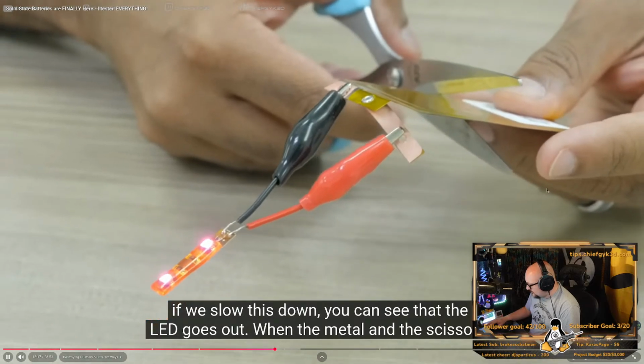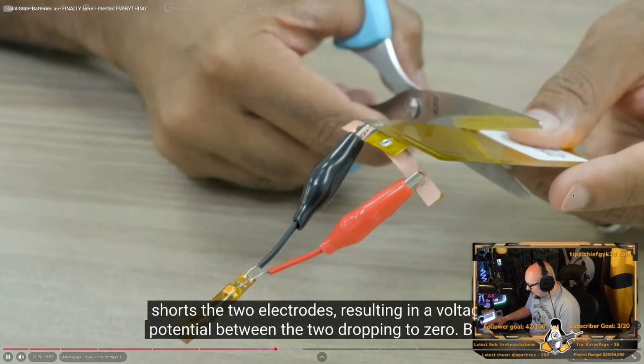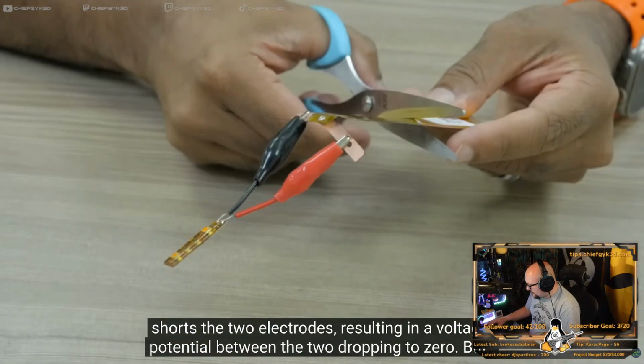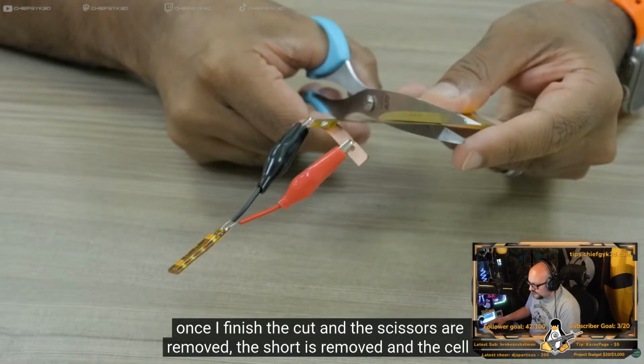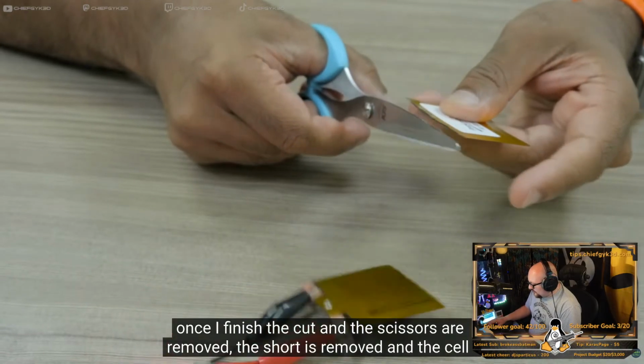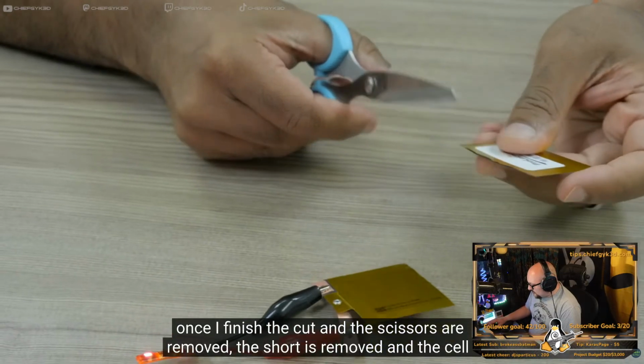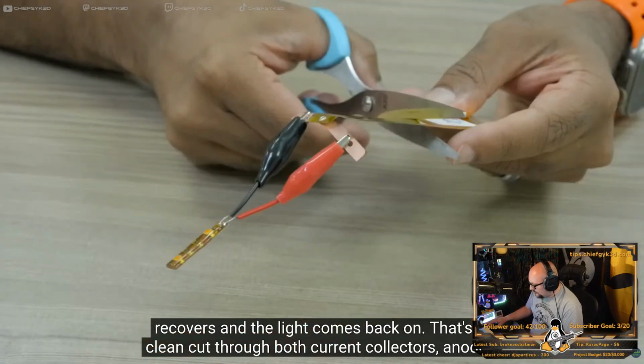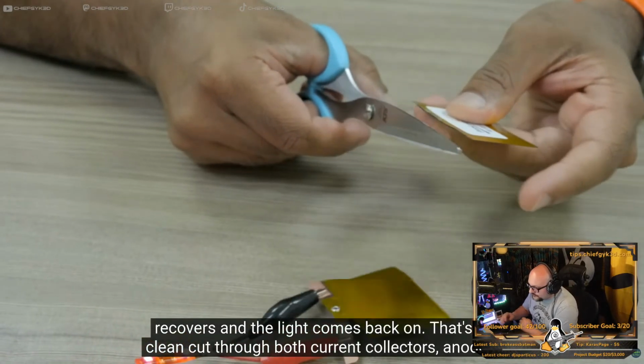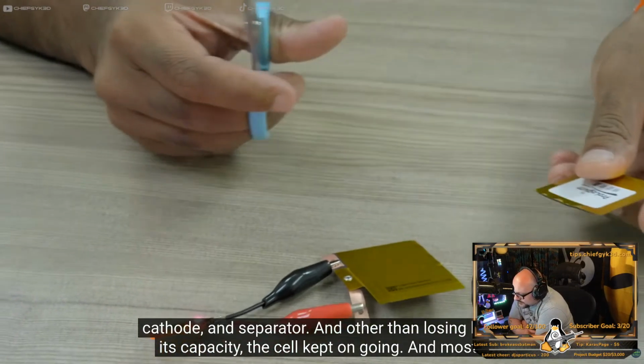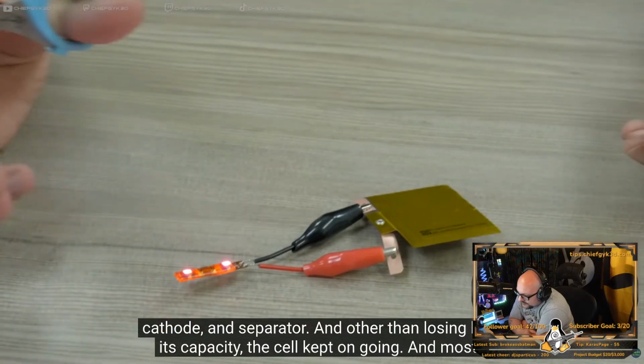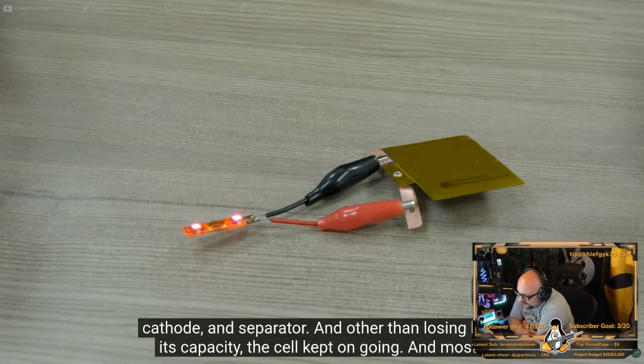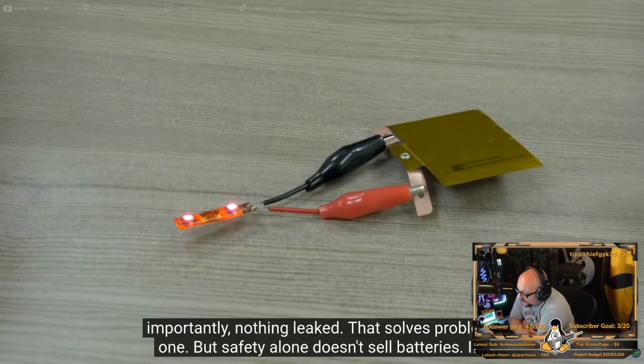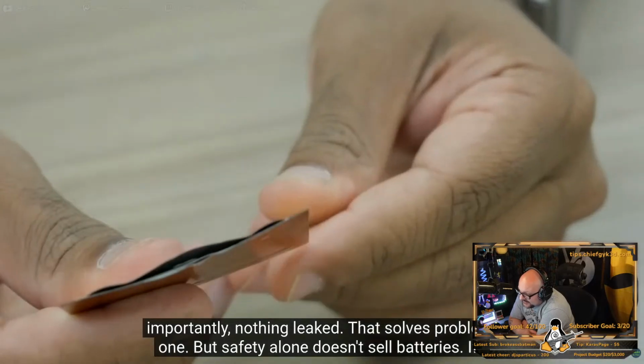The metal in the scissors shorts the two electrodes, resulting in a voltage potential between the two dropping to zero. But once I finish the cut and the scissors are removed, the short is removed, and the cell recovers and the light comes back on. That's a clean cut through both current collectors, anode, cathode, and separator. And other than losing half its capacity, the cell kept on going. Yep. Nothing leaked. That solves problem one.